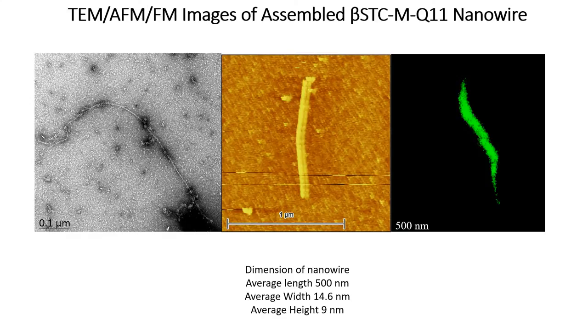Through transmission electron microscopy, AFM, and FM, I confirm the presence of these nanowires and also their dimensions, where the average length, width, and height are 500nm, 15nm, and 9nm respectively.